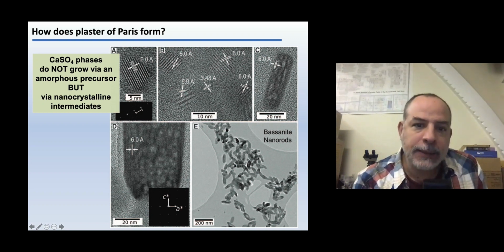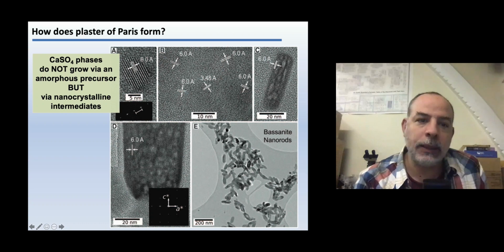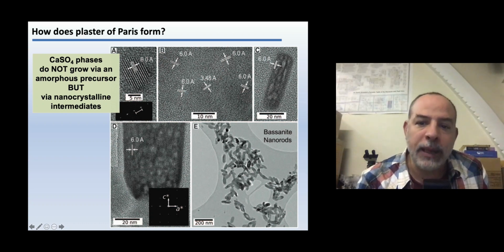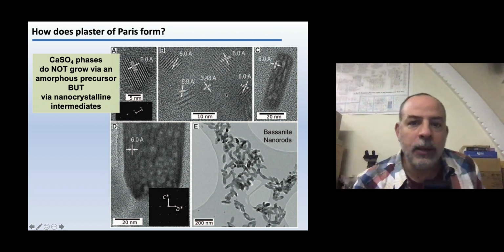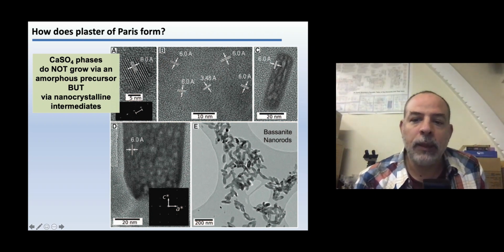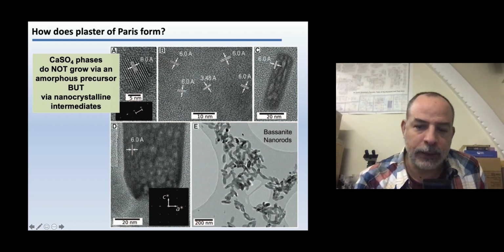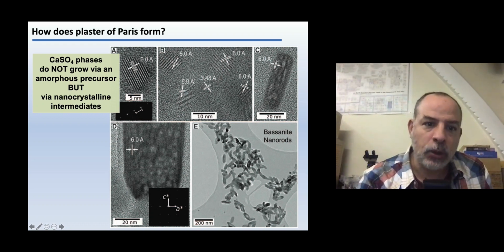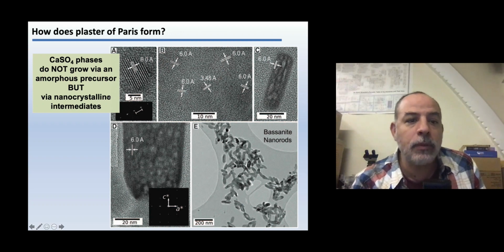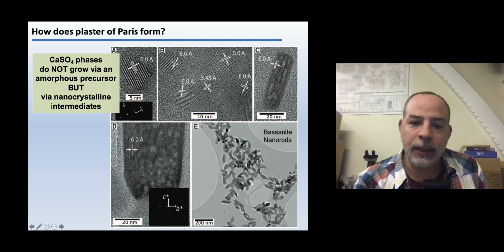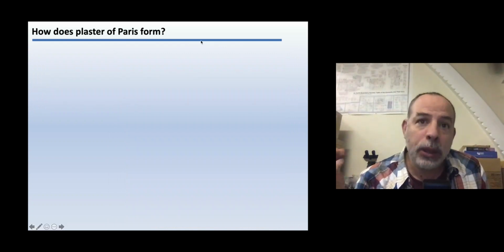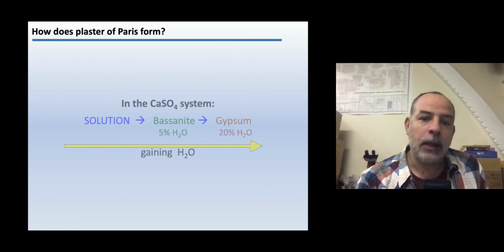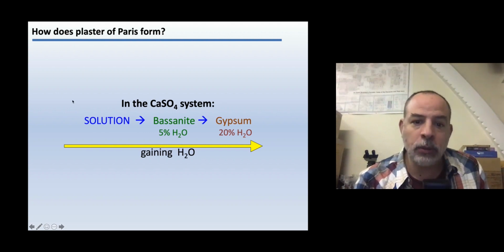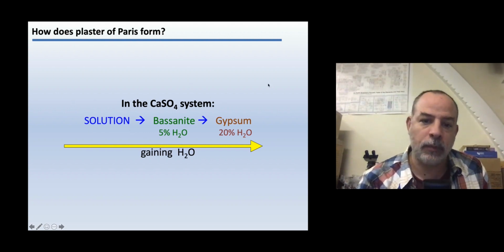And what happens is that some small nanoparticles made of bassanite form from the very early beginning, and they aggregate via oriented attachment, forming bigger rods of bassanite. And then this bassanite transforms into gypsum. So essentially what happens is that gypsum forms via nanocrystalline intermediates. Okay, we follow this using synchrotron-based techniques. Without synchrotron-based techniques, it will be impossible or very difficult to follow these reactions. And what we found is that yes, we go from solution, then to bassanite, then to this gypsum, gaining water.